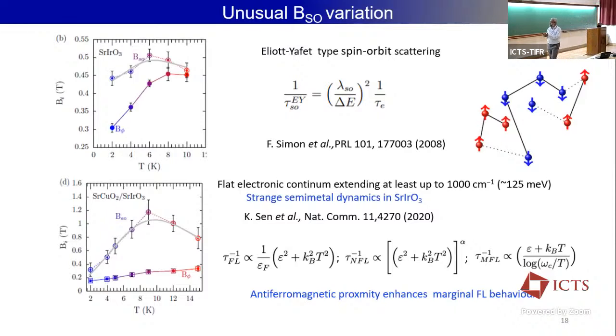And as I mentioned, generally these marginal Fermi liquid behaviors are very prone close to the border of antiferromagnetism. Here we are putting an antiferromagnet in proximity to this SrIrO3, and we see that it enhances the marginal Fermi liquid behavior.